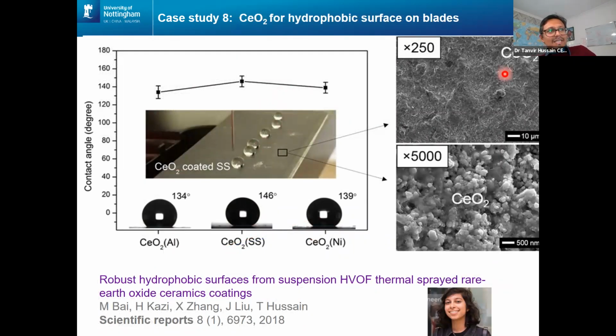Superhydrophobic: we were spraying ceria at the time, onto aluminium, stainless steel, and nickel. And the contact angle we were getting was around 146 to 150 degrees. You can see those nice water droplets. So the idea is, if you've got a ceramic coated substrate, the water will roll off, or even for ice phobic coatings, the ice crystals will not form. As a consequence, you can have a more robust coating, which can be superior to the polymeric coating that's currently used. That was Hafsa's work at the time.